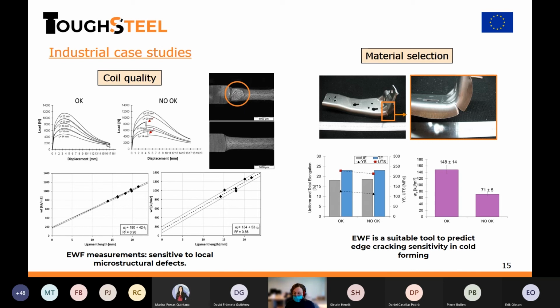So when performing the essential work of fracture, we found that the material that was more pure and had fewer defects had double the essential work of fracture of the one that was not okay. So this was a good way to show which material was best to choose for these cold forming procedures. So here are these two examples for the use of the essential work of fracture, and how we can apply that.